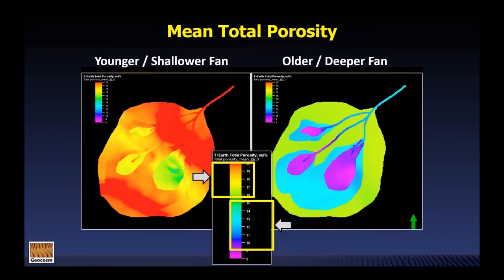What I find to be very interesting in looking at these two fans is a contrast in the porosity between the facies. Now, if we look at this part of the fan right here, where we have a close juxtaposition between the channel and the outer lobe, we see that there's quite a large porosity difference between these two facies. Interestingly, and perhaps not intuitively, we actually see higher predicted porosities in the outer lobe compared to what you would expect to be a better reservoir quality facies in the channel. Now, if we look at the equivalent area in the shallow fan, we see actually about the same total porosity between these two facies.